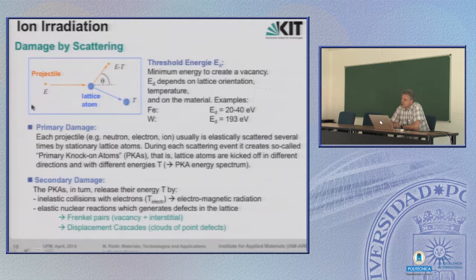There is a minimum energy which is required to displace such a lattice atom from its lattice place, and of course this depends on the material, on the specific lattice. With this we can subdivide damage in two sections. One is the primary damage. This means each projectile, this can be neutron, electron or ion, for the moment we stay for ions, is usually scattered not only one time, it's scattered several times through the lattice. It transfers energies to a multitude of several lattice atoms.